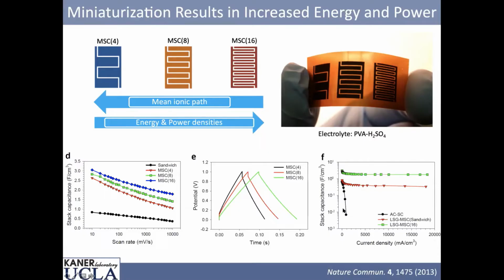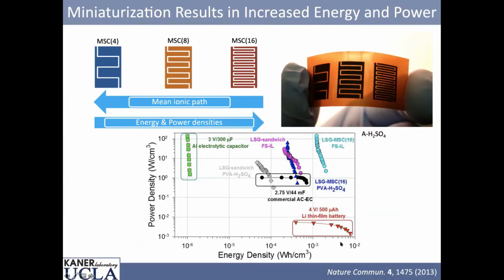They're much better than commercial devices, which fall off, and they're better than other things that have come before them. In fact, if we look at a Ragone plot, power density versus energy density, aluminum electrolytic capacitors are high power but low energy. Lithium thin film batteries are high energy but low power. And here are our different supercapacitors. If we go to an ionic liquid, we can get something that has the energy storage capacity of a lithium thin film battery and the power of an aluminum electrolytic capacitor. This just shows you what you can do. It may also tell you that lithium batteries aren't necessarily the best at scaling down, but you can make very high powered devices very simply.